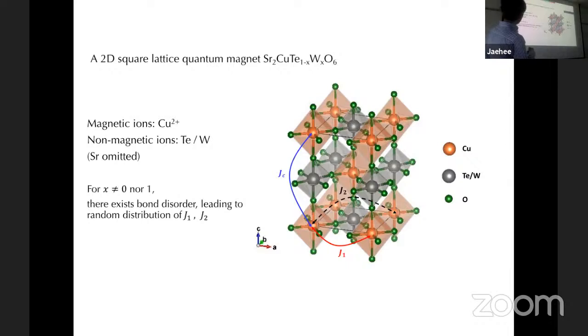All right. Now, if we have tellurium, pure tellurium, then because of quantum chemistry, the interaction between copper ions has to go through, because it's an eg electron and it's surrounded by six oxygens. It goes through oxygen and goes to tellurium, or tungsten, depending on what atom you have, and on to another oxygen and then copper. There's a superexchange path. And these are almost 90 degrees. These are J1, and 180 degrees will be J2, the second nearest neighbor interactions.